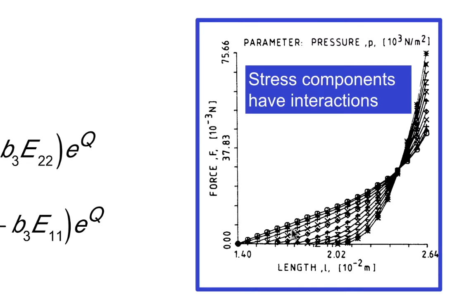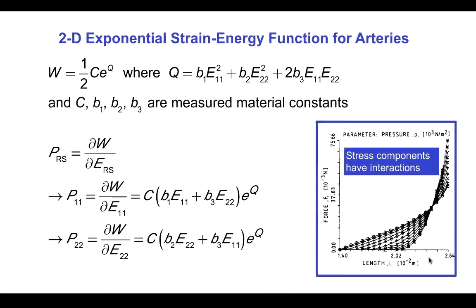testing of blood vessels, where here you see the length of the vessel and the force, and the different curves represent the force-length relation when the vessel is being stretched, if the vessel is also being inflated to different pressures. And you can see that there's a complex interaction between the circumferential stress due to pressure inflation and the longitudinal stress associated with axial strain.